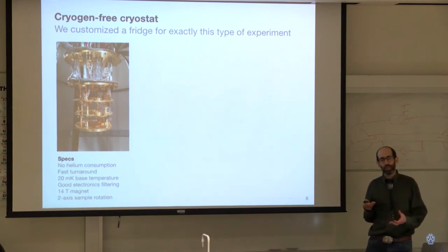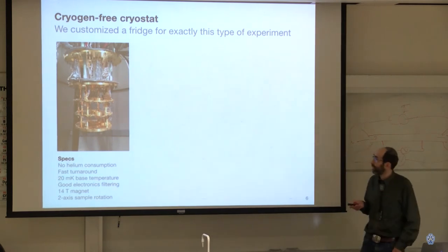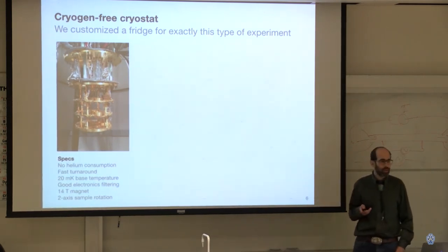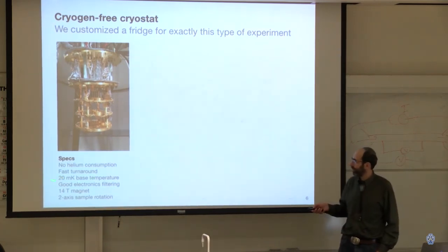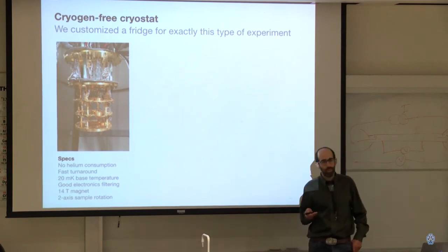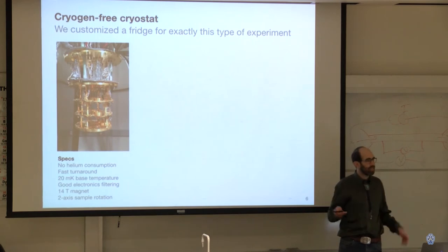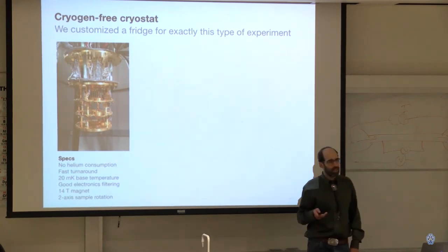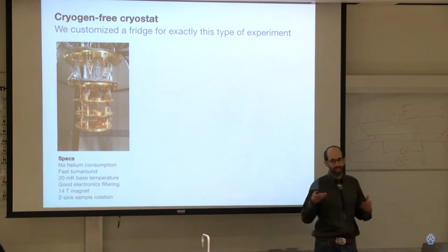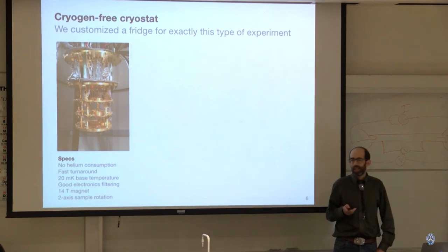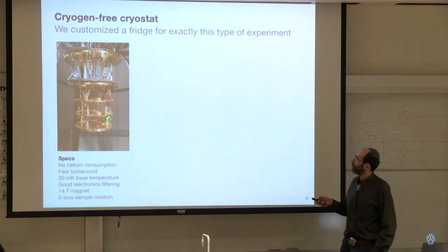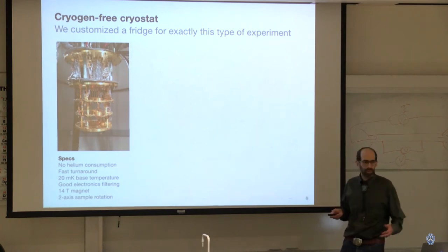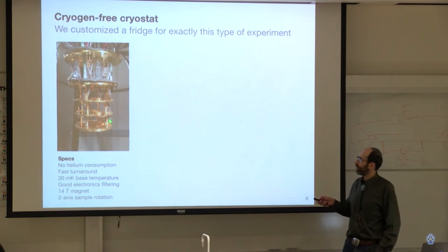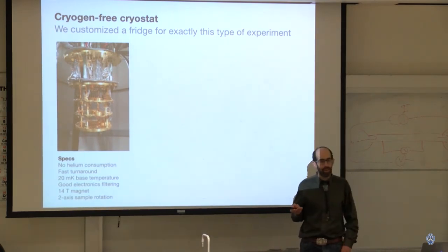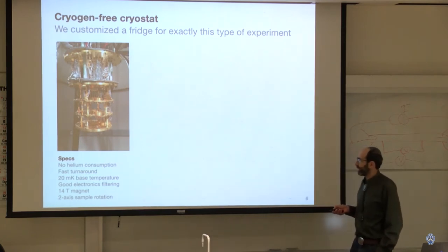So if you have to cool things down to very low temperatures, and it turns out we did for this project, then it normally takes a long time to do that. So we cool things down to tens of millikelvin, so hundredths of a degree above absolute zero. And you can imagine it takes a while to get all the heat out of something. When I was in grad school, it took a day, 24 hours, to get things cold, and that was if we were really working our tails off. So we worked with a company that made these cryostats and designed something that allowed us to insert a sample, to not warm up the entire cryostat, the entire refrigerator, but to insert a sample and to have it go from room temperature to cold in about 6 hours. So that was a really big deal. We could have fast turnaround.